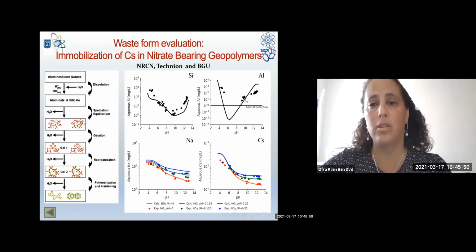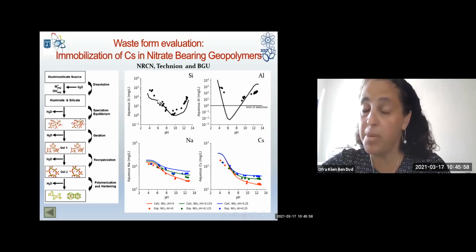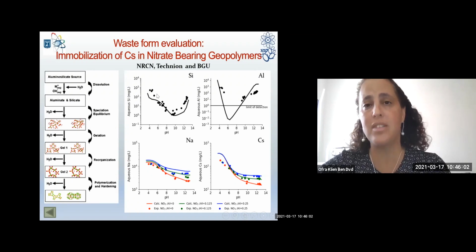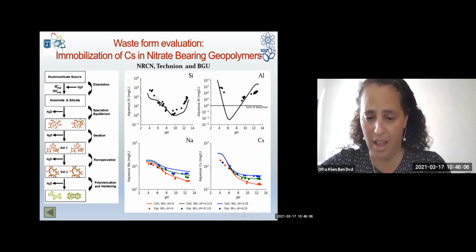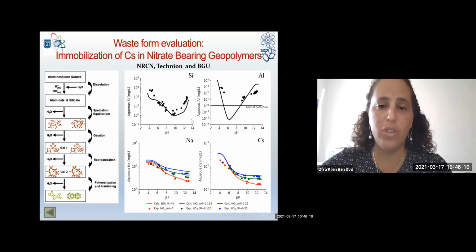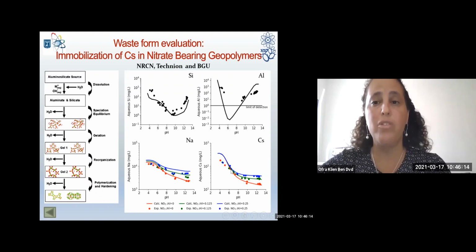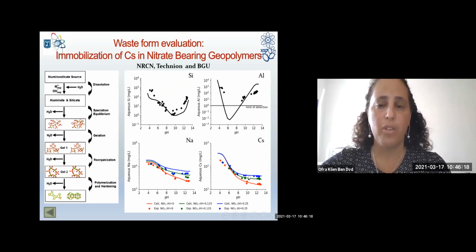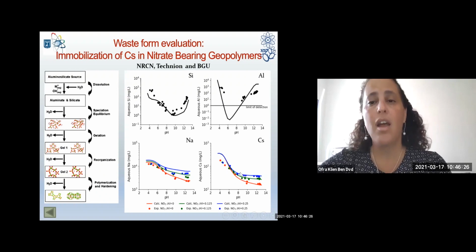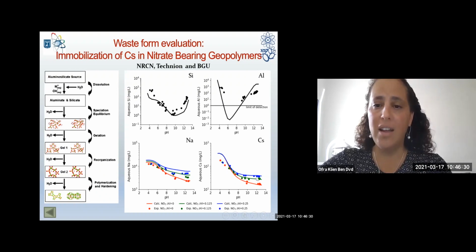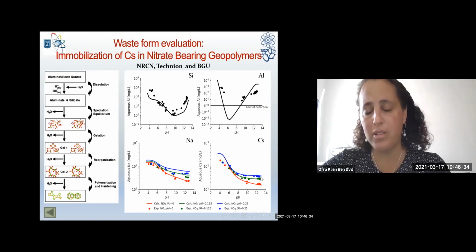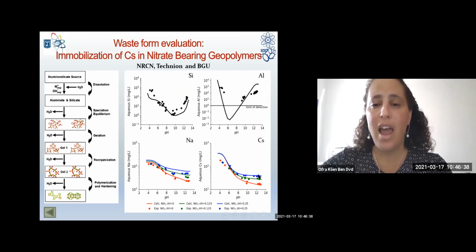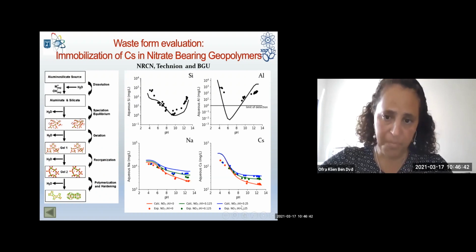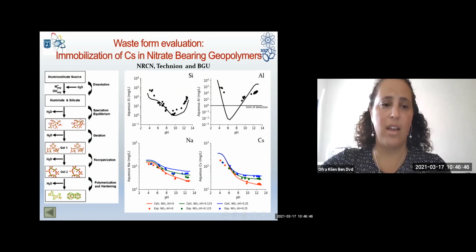And I just wanted to show you some of the tools that we use to estimate the compliance of this material. We basically use geochemical modeling on a specific framework designed for cements and geopolymers, and specific databases like CEMDATA with a software called GEMS, also with PHREEQC, to simulate how contaminants will be released from the matrix and what are the best conditions for the matrix to be stored at. This example shows the retention of cesium, as I said, another important contaminant. You can see that when we have high nitrate content in the geopolymer, which happens because of the radioactive streams, we have less retention than when we have no nitrate, and we could very nicely simulate the results.